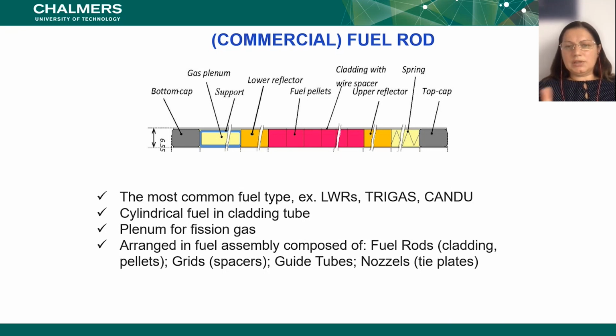when you start producing. This is, by the way, a fuel rod which is made for oxide fuels. And in their case, we can talk about significant release of gases, and also we have the volatile products which are released, which will end up in the gas form. So that means this plenum will fill gradually with different compounds and gases resulting from the irradiation. So knowing how the fuel rod looks like, then you already have a very good case where you can prevent and know the future behavior. So this is the safety of the fuel pin, we call it.